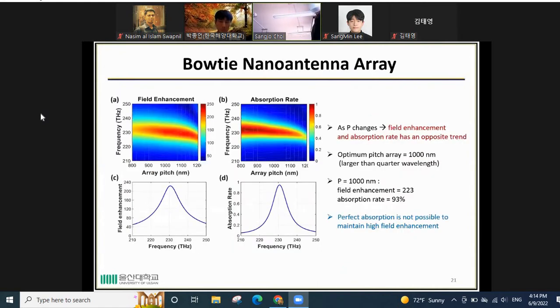And this is the electric field enhancement and absorption rate as we change the array pitch size and frequency. From this we can also see that as we change the pitch, the field enhancement and absorption rate have opposite trends. But from the maximum, we pick the optimum array pitch of around 1 micrometer, which is larger than the quarter wavelength. So this is the field enhancement and absorption rate for the 1 micrometer pitch size.